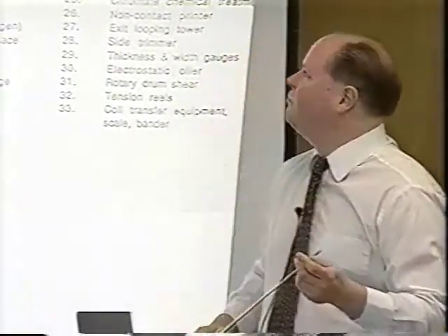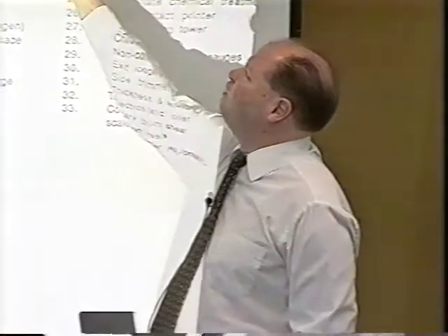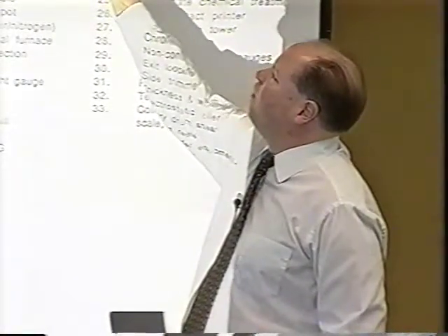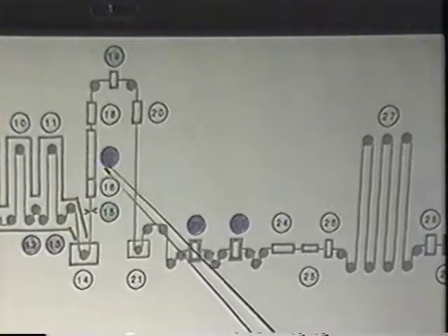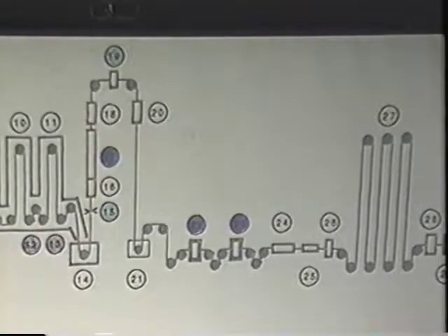So there's a couple of manufacturers that make a gauge that does that, and we happen to have one of them. So we can actually measure the galvanneal coating. We measure the percent zinc in the coating, of course, for the coating weight, and also the percent iron in the coating. So that's kind of difficult for most lines to do.